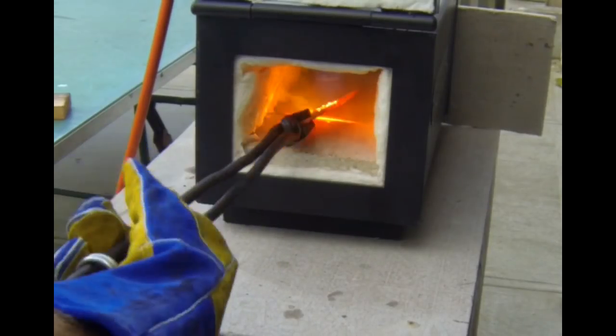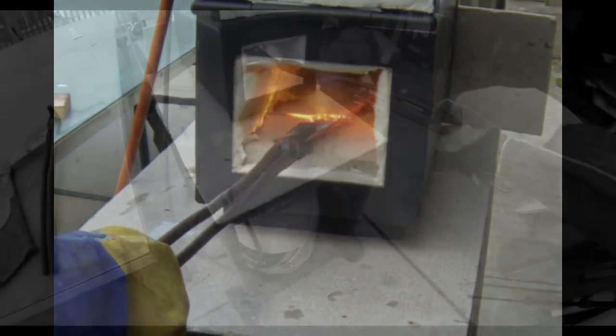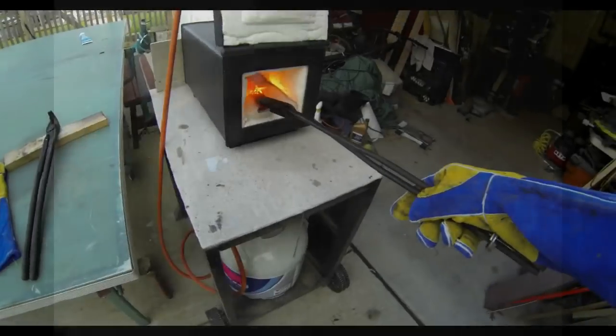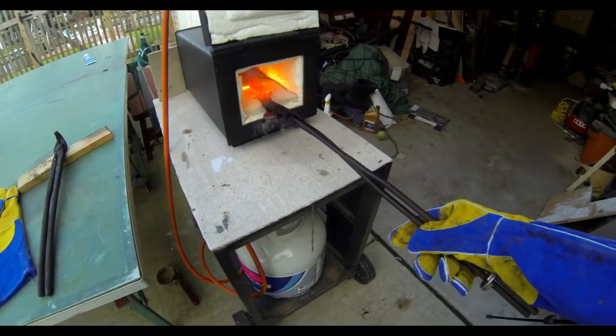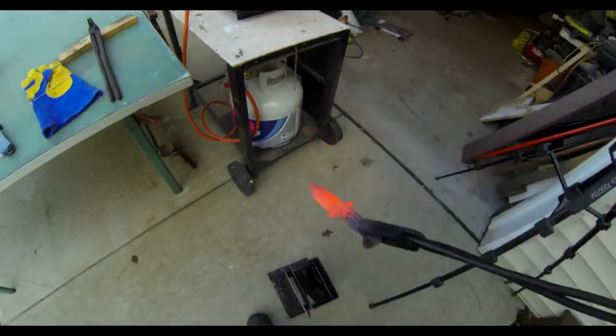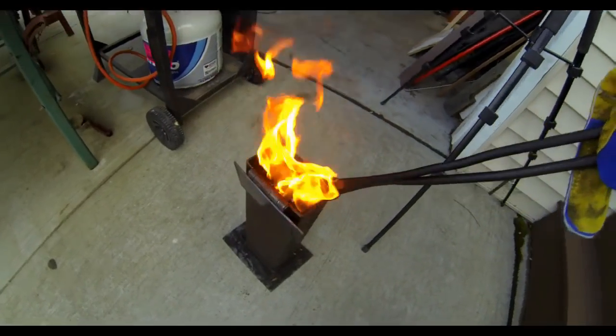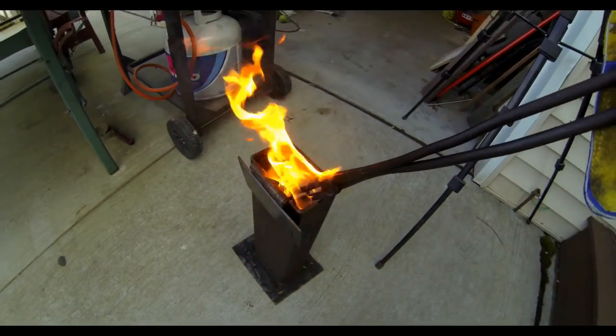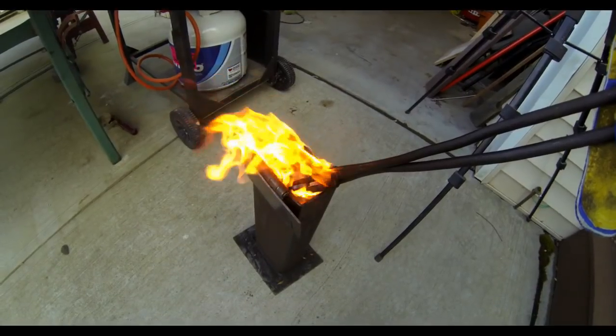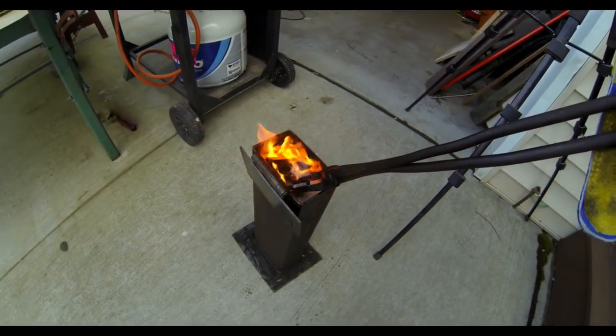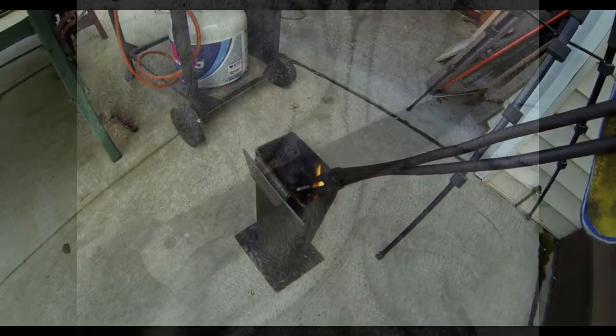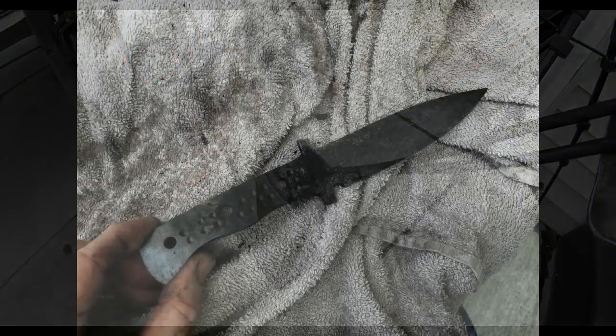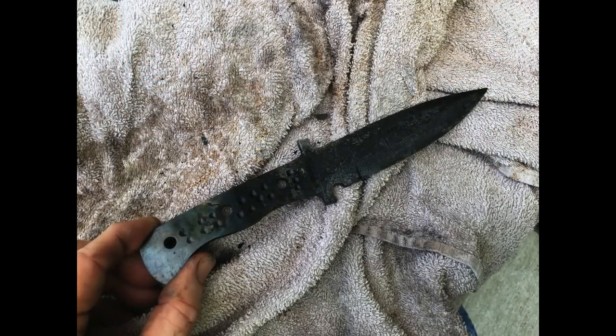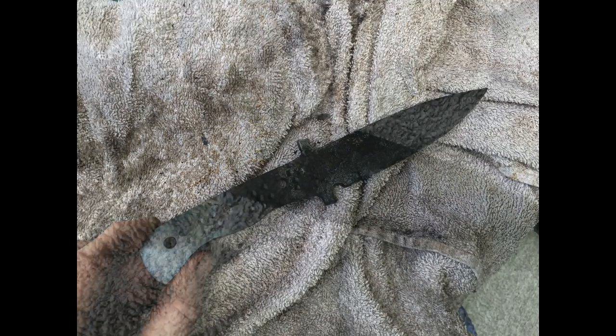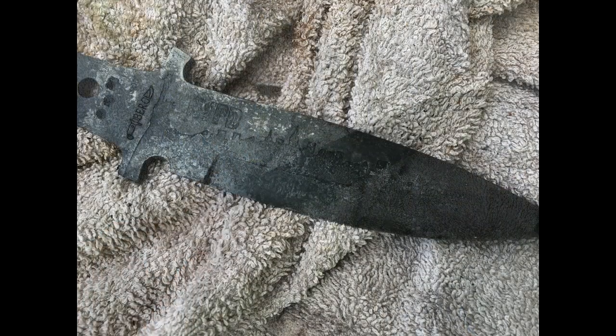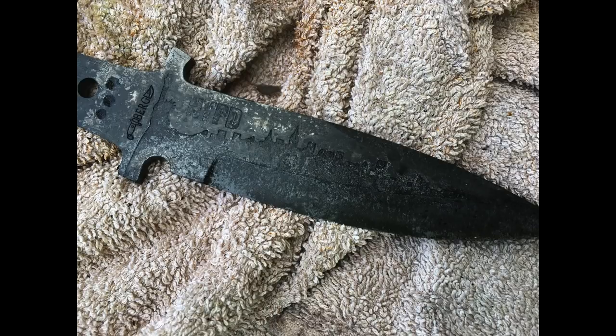And I have a magnet stuck on the side of the forge. I just test it and make sure it's non-magnetic. Once you see the color of the material at non-magnetic, then it's very easy to repeat that. The blade gets quenched in quenching oil. That makes that 1095 nice and hard. It then also goes through a tempering process. It goes in an oven, 375 for 2 hours, and then I let it cool overnight without opening the oven